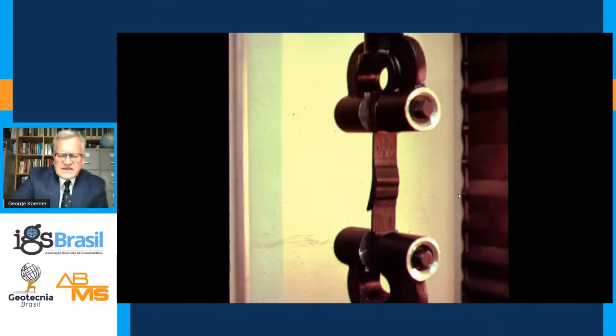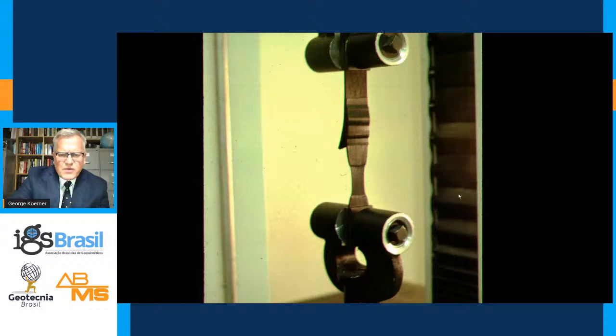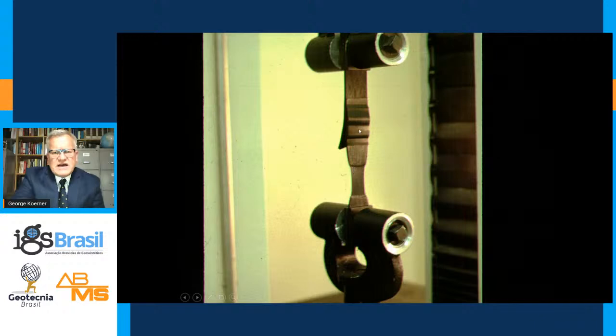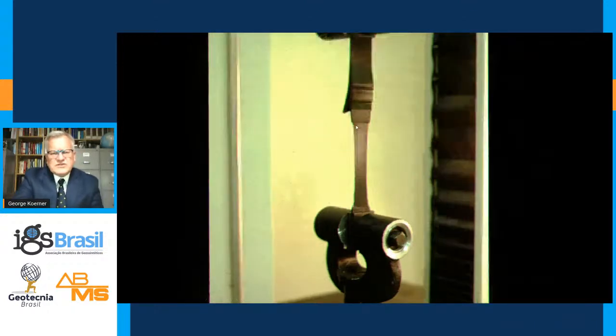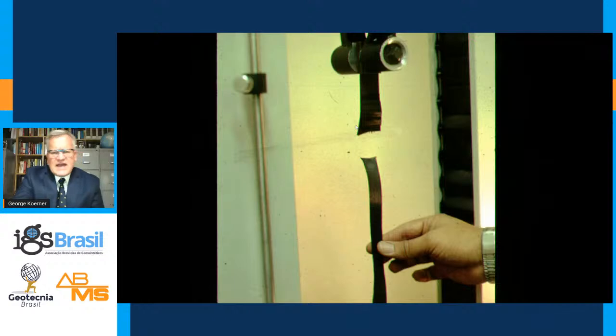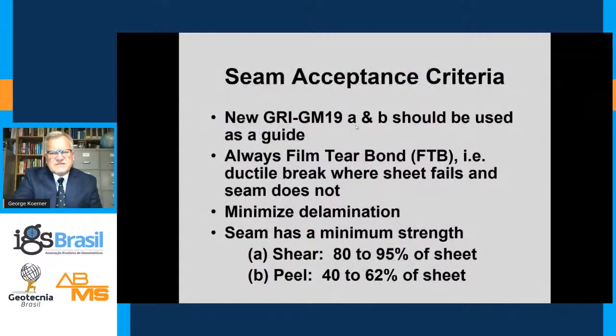Here you see the shear test set up. We're pulling, and here in the bottom you see a yield of the material. The bond was stronger than the material, which is a good indication. Again, a ductile failure, you'll see those fibrils of the material, and this is a very successful test.